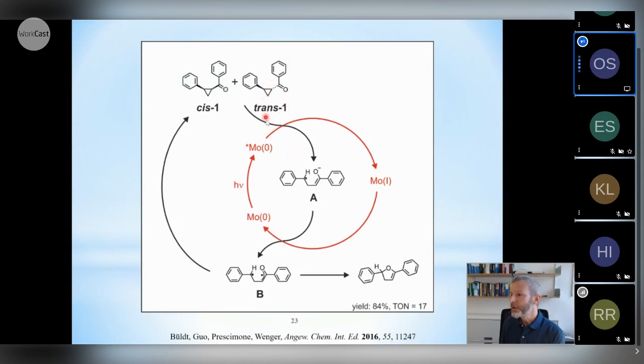Presumably the first step is key. The starting material is reduced by the photoexcited molybdenum zero complex to this enolate intermediate A, and this can then undergo backward electron transfer with the oxidized molybdenum complex. That will lead you to the initial molybdenum zero starting point and to this diradical intermediate B, which can then react onwards to the product. We've never optimized this reaction. We didn't really care at the time. It was a proof of principle, but you can see the yield was low, and likely, had we tried, it would have stayed low because there was a problem with robustness.